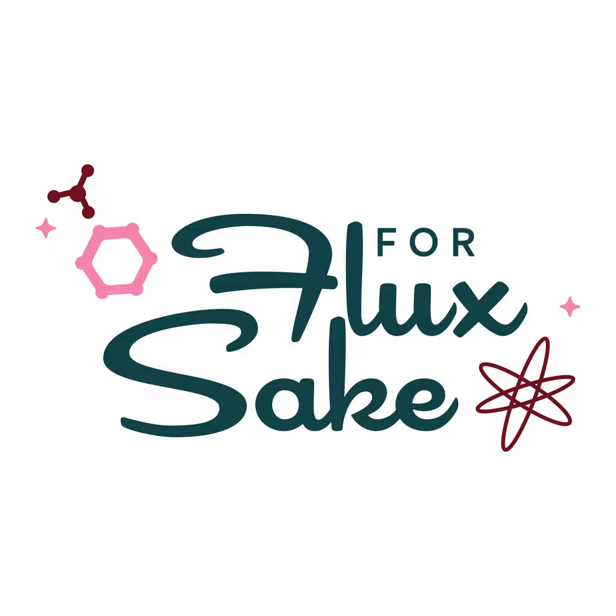That mullite that we form is actually forming from the kaolin. And so if you want things to be more translucent, you'd need less kaolin. And about 50% is as far as you can lower it and still have that clay body hand formable, so you can throw or sculpt or whatever. But when you're making stoneware, it doesn't need to be translucent. So you just put in a ton of clay because it just is easier to work. So, you know, it's a bit of what it's not.